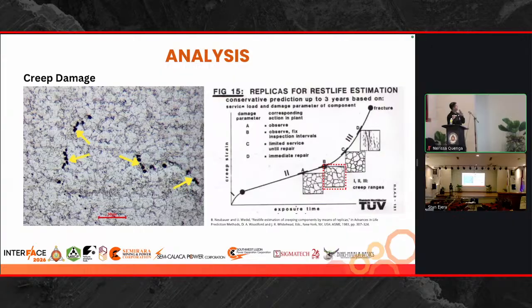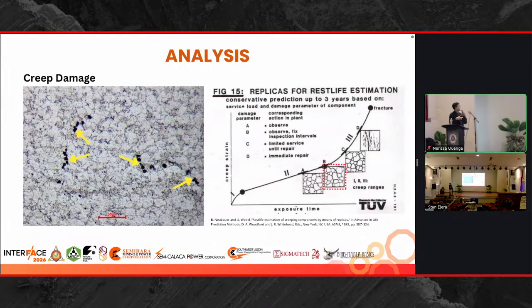So we have our reference here, and these are the stages of creep. So we have primary, we have secondary, and tertiary creep. And from the qualitative assessment of this micrograph, we have concluded that this specific component is currently around this part in its creep stage. So it is on the secondary stage, and the recommendation that we can give for this is to further observe and monitor the development of these creep voids if they orient to form microcracks. But intervals should be adjusted to make it more frequent.